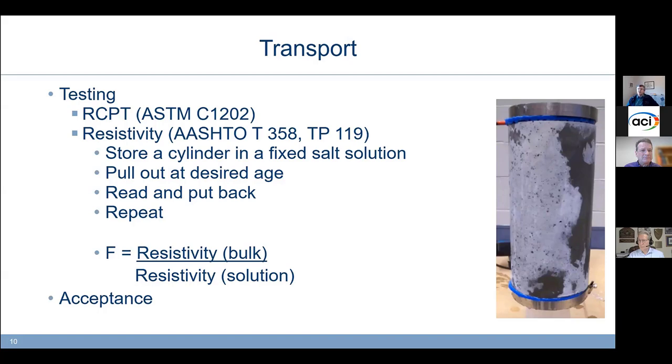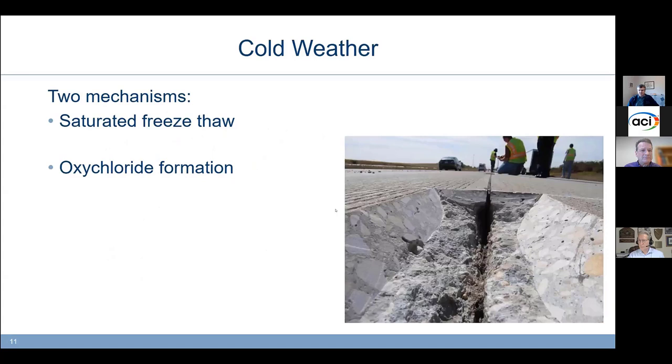For curing, we recommend stripping cylinders and taking them out of molds at 24 hours, putting them into a fixed-salt solution, pulling them out, putting them under test using either the 4-pin approach or through-the-sample approach, then putting them back in the bucket. Pull them out again at 7 days, 28 days, or whatever your acceptance testing requires. Even at 28 days, you can run a compression test on that same cylinder. This is proving to be a far more efficient way of understanding the potential life of our mixtures — a fairly quick, easy, cost-effective test that we can run for acceptance.